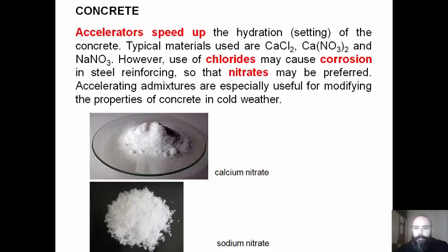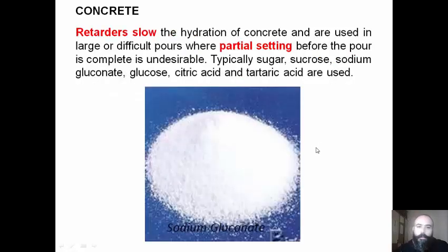Typical materials used are calcium chlorides, calcium nitrates, and sodium nitrates. However, use of chlorides may cause corrosion in steel reinforcing, so nitrates may be preferred. Accelerating admixtures are especially useful for modifying the properties of concrete in cold weather.